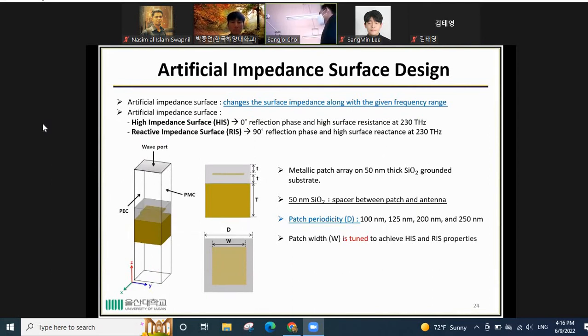Since our design is using an artificial impedance surface instead of the grounded reflector, I will explain the artificial impedance surface first. We design an artificial impedance surface that can change the surface impedance along different frequency ranges. In our design, we design a high impedance surface with zero reflection phase and high surface resistance at resonant frequency, and also a reactive impedance surface with 90-degree reflection phase and high surface reactance at 230 terahertz. So this is the design of the artificial impedance surface.